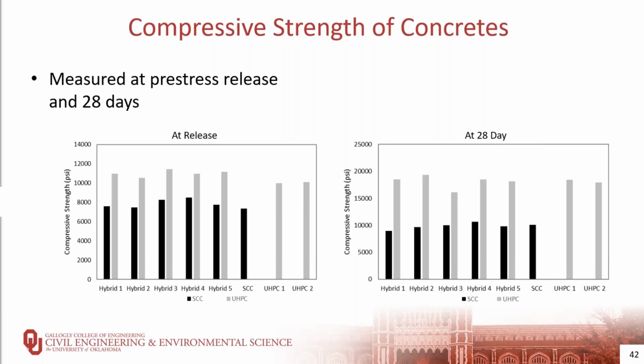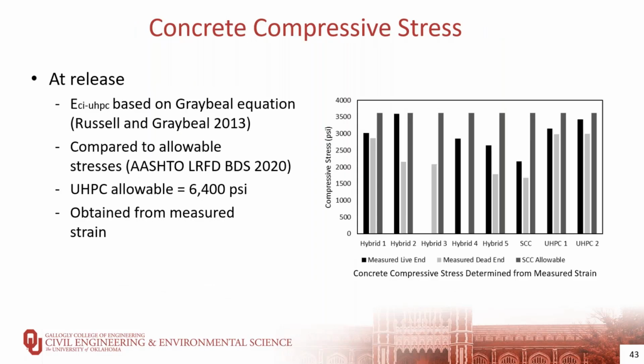Before we start talking about the results for the compressive stresses, here is the compressive strength for all the girders at release and at 28 days. The SCC averaged around 7,400 psi at release and 9,500 psi at 28 days, whereas the UHPC averaged 10,000 psi at release and 18,500 psi at 28 days in terms of compressive strength.